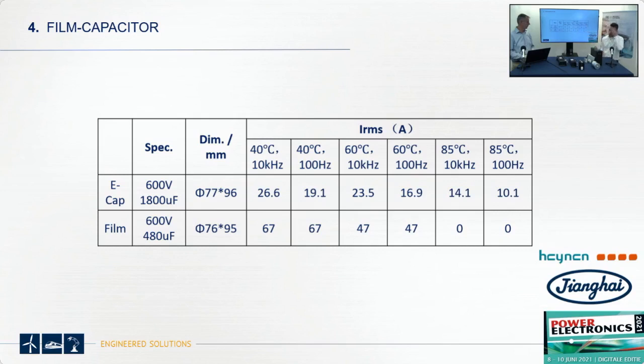And for film caps, we have specified 85 degrees, and this is including the current. That means when you have 85 degrees in the ambient temperature, it's not allowed to use current, because you increase the temperature inside the capacitor, similar to the ECAP. But this is the technology difference between ECAPs and film caps, that it's possible to use current over 85 degrees, and for film caps it's not possible to use currents over the specified temperature. Okay. But the currents under the specified temperature are much higher compared to the ECAPs. Okay. In the same case, and with a much lower capacitance.